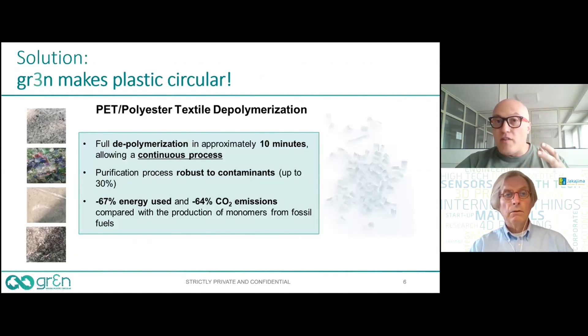This is an example of our results. We started from very contaminated material — for example, white bottles used for milk, colored bottles, plastic trays that contain 15–20% polyolefins (polyethylene), or textiles containing 30% polyurethane. From a mix of these monomers, we were able to produce this polymer — you can see on your right — which is perfectly colorless and beautiful.